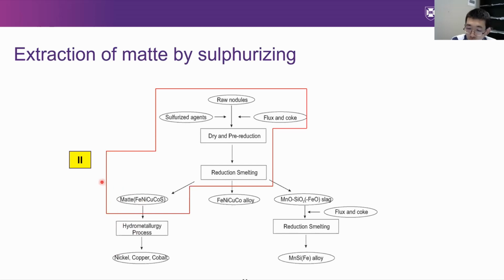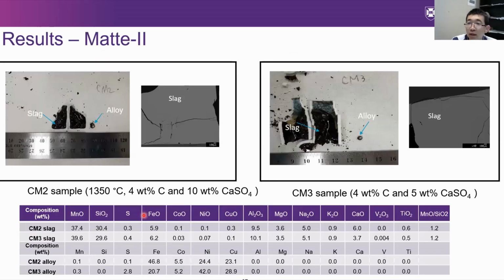This is maybe more favorable for the market product. However, we just did a preliminary experiment to produce this matte, where we doped the sulfur as calcium sulfate, at 1350 degrees with 4% carbon as a reductant. This is from a previous study, and then 10%.